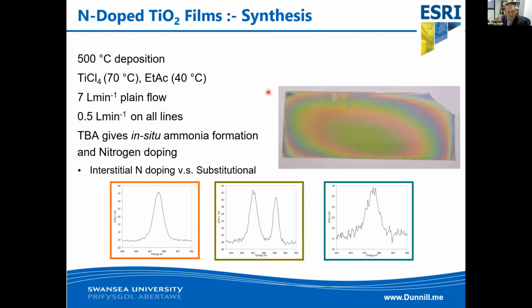The synthesis is carried out at 500 degrees centigrade using TiCl4 and ethyl acetate to give us our titanium oxide. And then we have t-butylamine to give ammonia formation in situ. What we found here that was actually really quite interesting is that when you dope titania with nitrogen, you have 2 different options. You can put the nitrogen in exchange of an oxygen, which is a substitutional doping, or you can add it to the interstitial sites within the crystal structure.